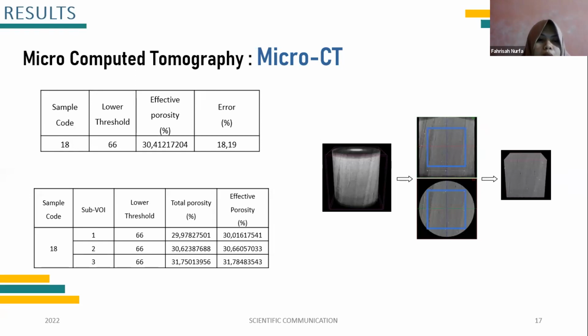This error can be caused by the cutting before, so not all areas of the sample are analyzed, and differences in the capability or resolution of the laboratory measurement and CTAN calculations. In addition, porosity calculations are also carried out on the sub-VOI, which is a smaller area than the sample image. It is found that the porosity value is still quite uniform in each area.